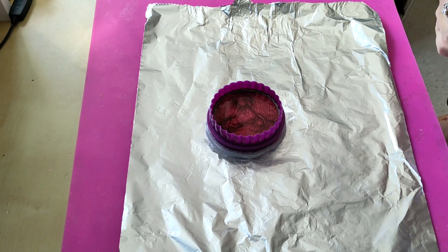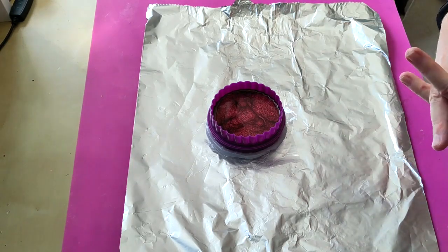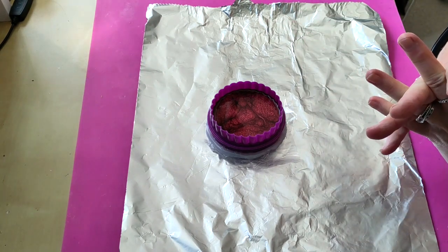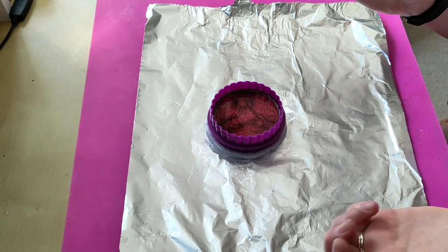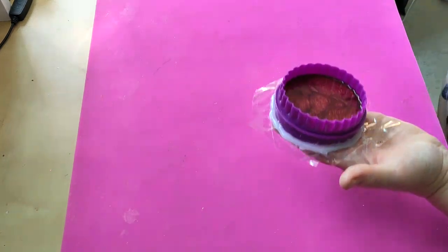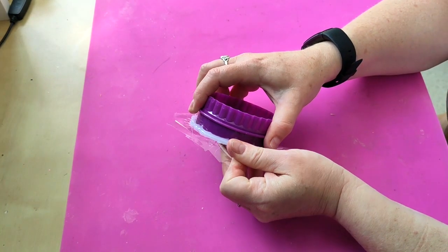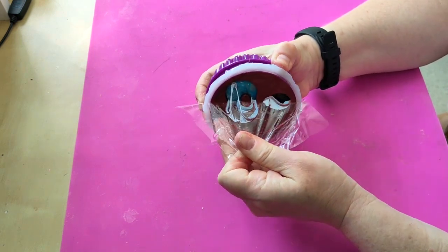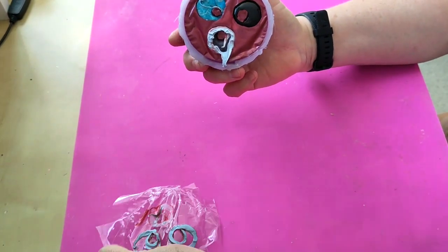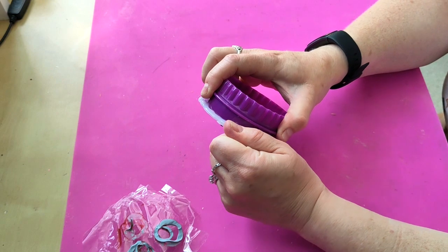Good morning! It's been 11 and a half hours since I poured this. It can be demoulded after about 8 hours, but you need to leave it the full 24 hours to let it finish leaching moisture before you can pour resin in. I'm going to demould it now so the inside parts can carry on degassing and getting rid of any moisture. It didn't leak, which is awesome. I need to pull the foil out of the way — it's making a crinkling noise. There's a sticky blue tack mess; hopefully that will come out of the silicone. I need to break the hot glue off.